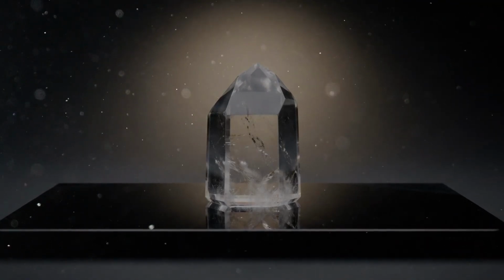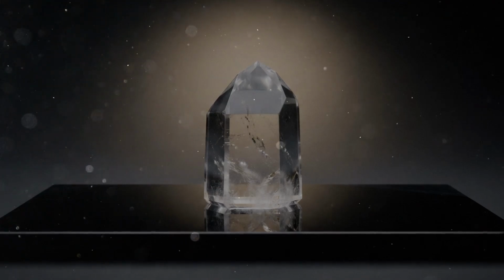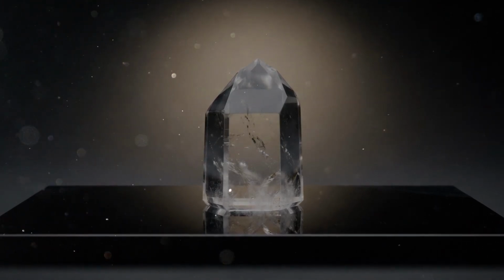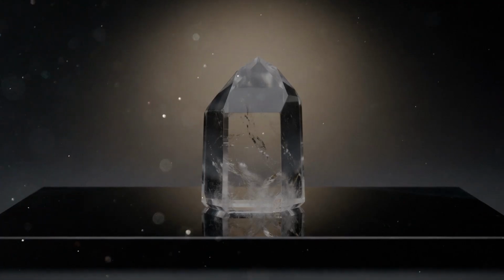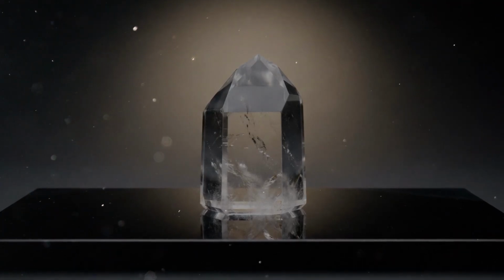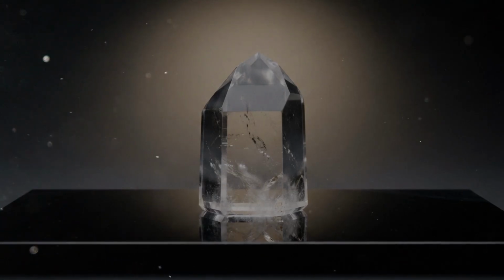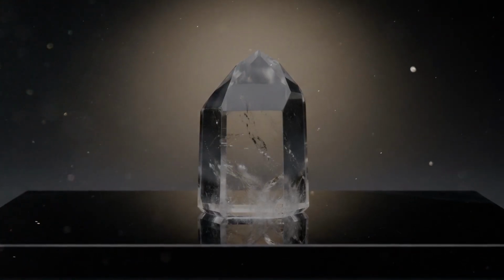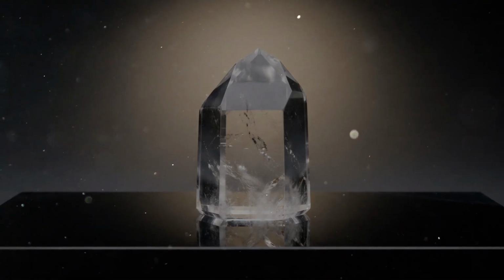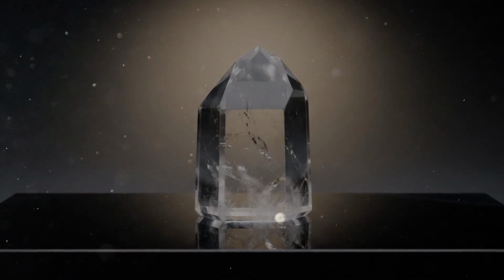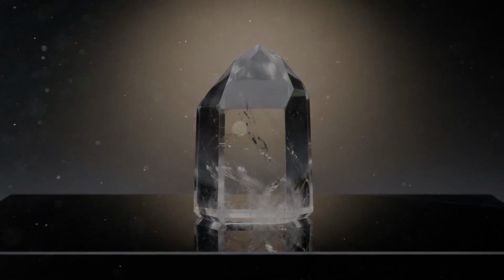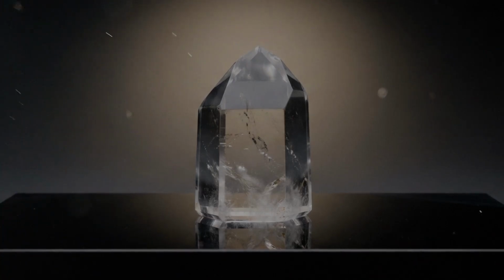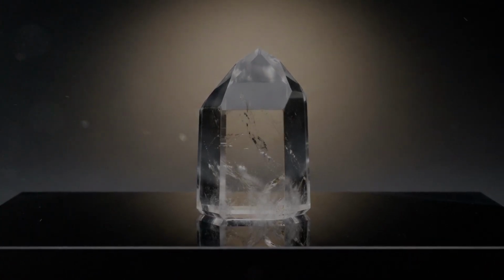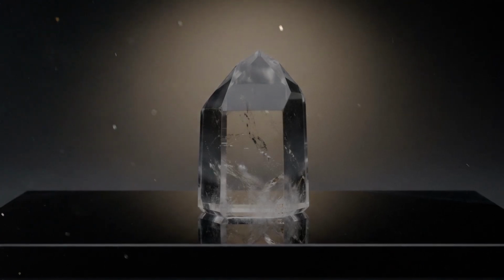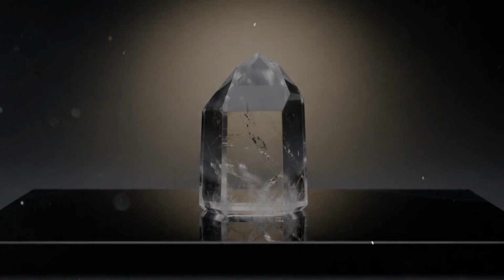The intensity of smoky colour depends on two factors: the amount of aluminum in the quartz and the radiation dose it received. Some smoky quartz from areas with high natural radioactivity is so dark it's almost completely opaque. Collectors prize these dark specimens, while jewelers often prefer lighter material that shows more transparency. Interestingly, smoky quartz is one variety where heat treatment can remove color rather than enhance it. Heating smoky quartz will often drive off the color, leaving clear quartz.